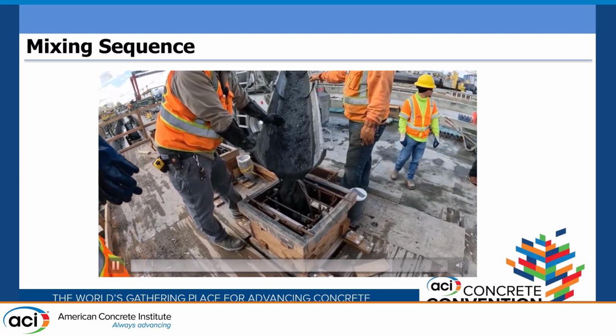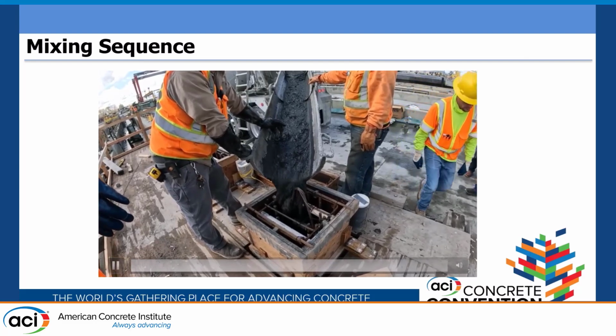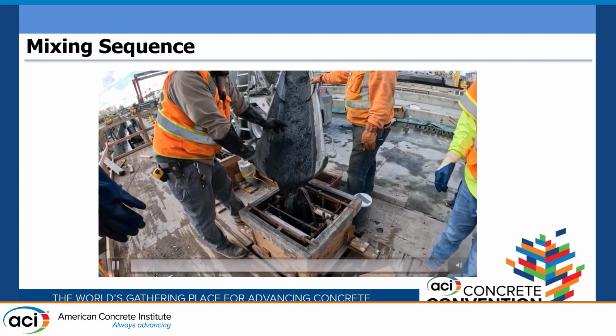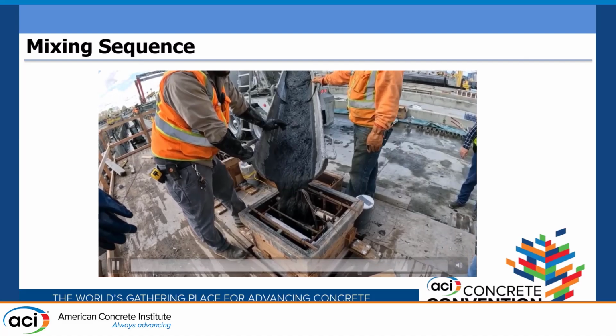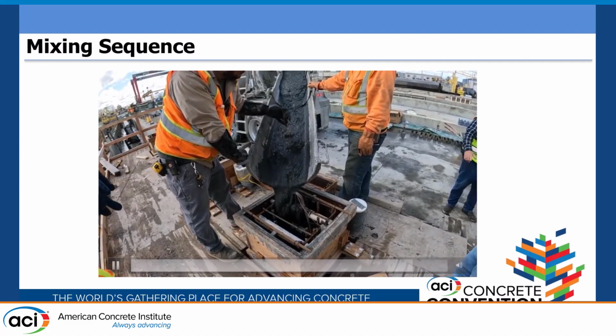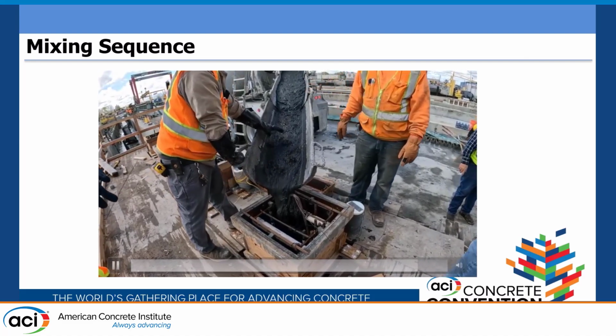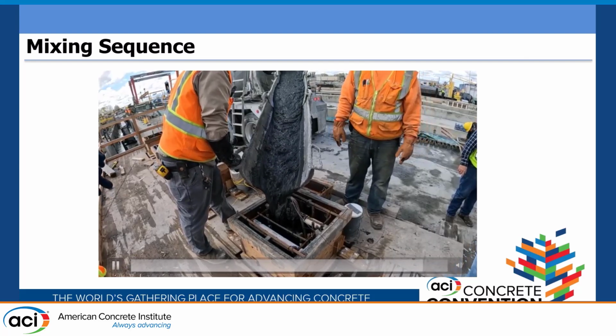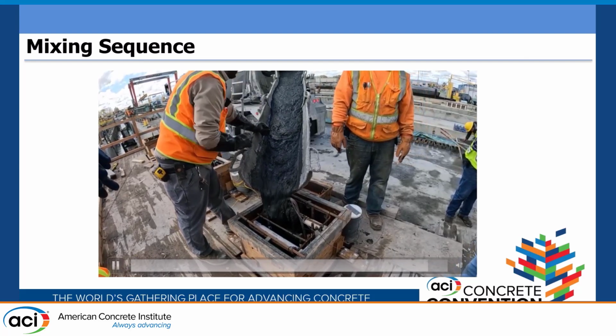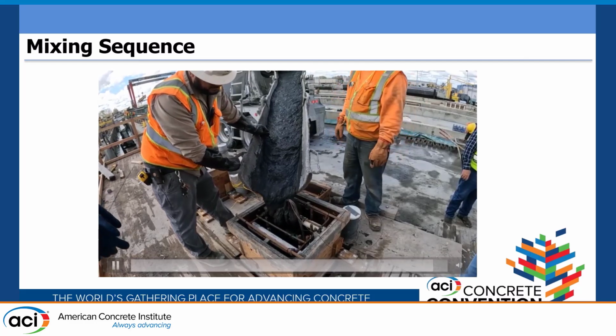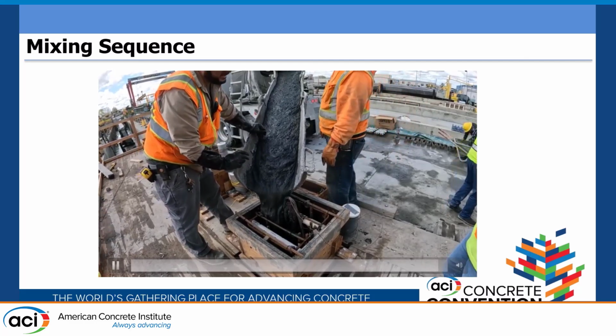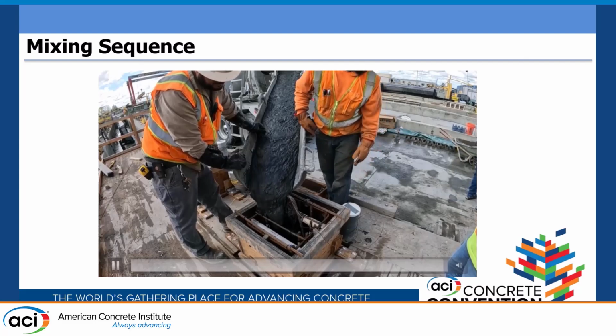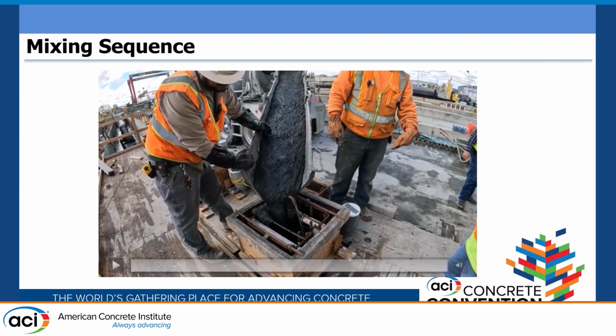It has some fiber segregation. We did mix them in a high shear mixer and found it's okay, but of course we were surprised that truck mixing gives a little bit of segregation. But again, when we were putting it in the column, we didn't have any issues because it's just hollow, so we didn't have fibers going into the reinforcement.